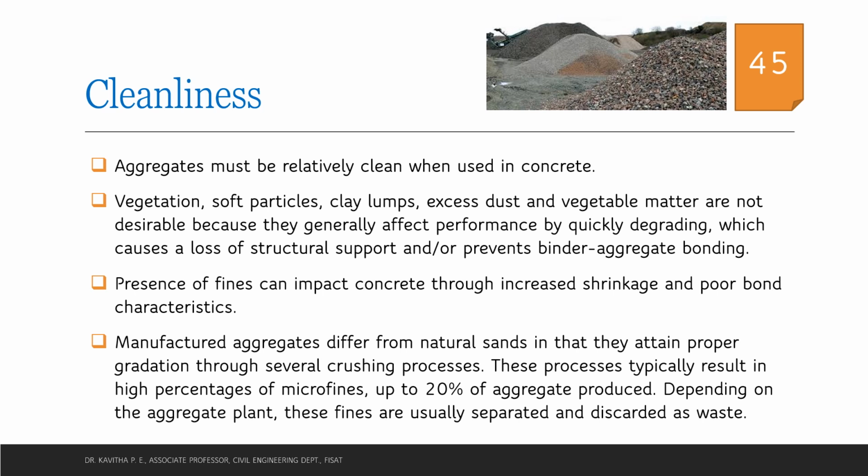When we are considering manufactured aggregates, they pass through several crushing processes. During this process, a lot of microfines are created. Around 20% of the aggregates will be converted to microfines. These microfines are to be removed before the aggregate is dispatched for concreting. Otherwise, these microfines will cause shrinkage in concrete, and it will in turn cause cracks in concrete.